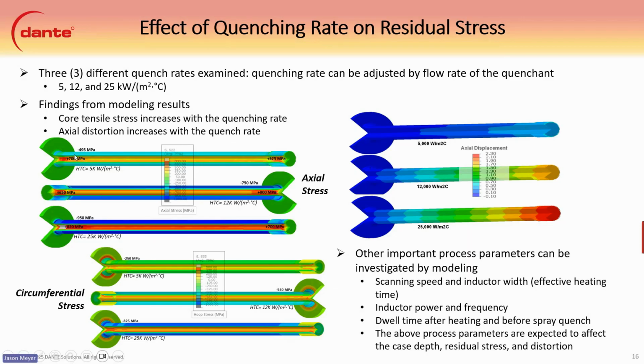The slower quenching rate also gave us lower compression of the surface, and then obviously a lower tension to balance it out inside the part. So as long as we reach the mechanical properties here, that one will work pretty well. The circumferential stresses are shown here as well. They mimic the axial stresses for the most part. There is a higher magnitude of stresses, compressive and tensile, in the higher quench rate model.